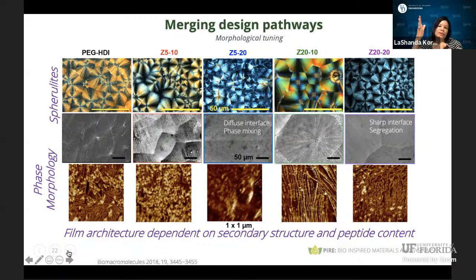For the Z5 system, if you go up to the 20, you see more diversity in terms of the Maltese cross patterns and the spherulitic sizes and structures, which is really driven by this phase mixing that occurs in these materials. So you have more of a diffuse interface, and that's why you have more globular types of structures with a mix of fibrillar structures in the Z5-20. For the Z2010, you have much larger spherulitic structures with really nice sharp interfaces in these systems, really driven by this overall segregation behavior. And again, AFM shows really nice phase morphology. For the Z2020, you also see changes in the overall spherulitic organization, really sharp interfaces and nice phase segregation. So now we can think about this film architecture and the mechanical properties, which are really dependent on the secondary structure and the peptide content.